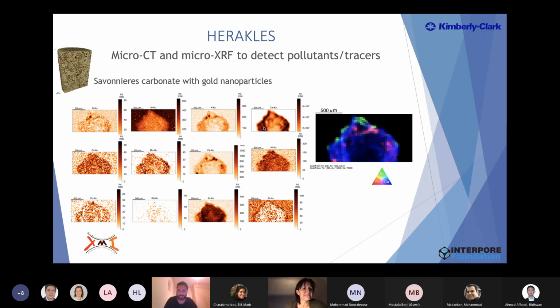But I wanted to test the sensitivity, so I took a limestone with gold nanoparticles to see if the system could detect this, because the gold nanoparticles were in the order of 30 to 60 nanometers diameter. Here you can see it was very sensitive for the gold, shown in green. But you can also see that in the middle we are missing information, because XRF only gives information about the surface area.